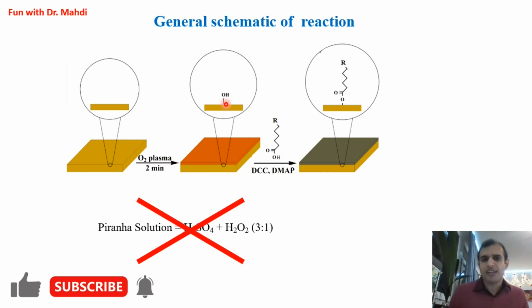Now you have hydroxyl on the surface, and with the esterification reaction, you want to cover the surface with this compound. You need to leave the substrate in this compound for 24 hours, and you also need two catalysts, DCC, dicyclohexylcarbodiimide, and DMAP, dimethylaminopyridine.